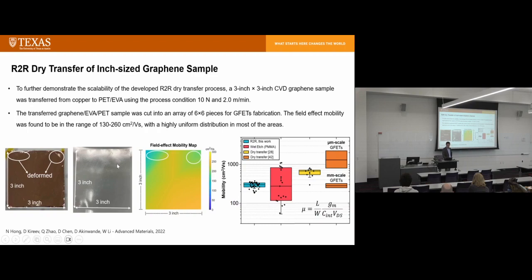Then we use field effect transistors to measure mobility of the sample. So this is the map. We sectioned it into smaller pieces, 6 by 6 pieces of samples, and then we use those pieces to build GFETs, and then we use the GFETs to measure mobility. This way we can measure mobility at each location, and then we can map the quality of the sample. In the end, we got very uniform quality of the sample, except there are 2 corners. Those 2 corners are where we used tweezers to pick out the samples, so the samples were damaged a little. So these 2 corners don't have very good mobility measurements.